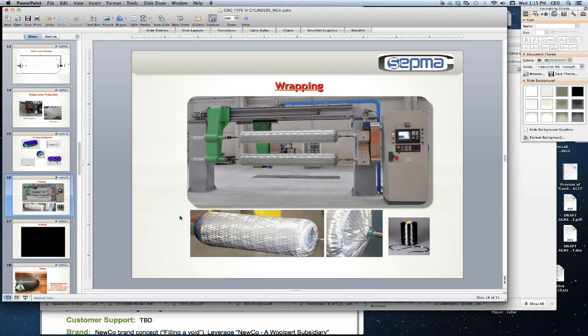It's typically done in machines like the one that you see up on your screen right now. It's a CNC controlled machine, and it comprises of the now rotomolded component, which acts as your mold, and you wrap your filament around it. In this case, we have two components that are being done at the same time. You can see as much as 3 typically in the business, and for smaller components even up to 6. But that all helps just maximize production and speed.